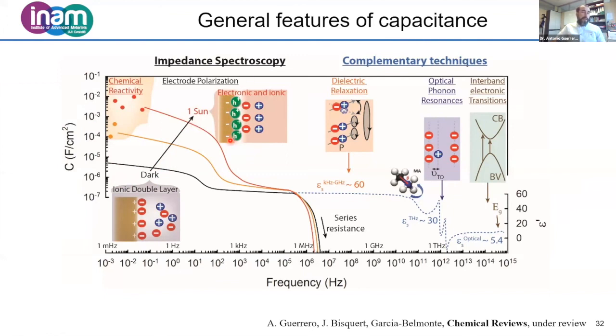And depending on the device configuration, at still lower frequencies, in the range of millihertz and tens of millihertz, we may be able to see noise, which is usually connected to the chemical reactivity of these ions in the presence of loads of charges, and with the photopotential generated by the semiconductor that are able to do electrochemical reactions.